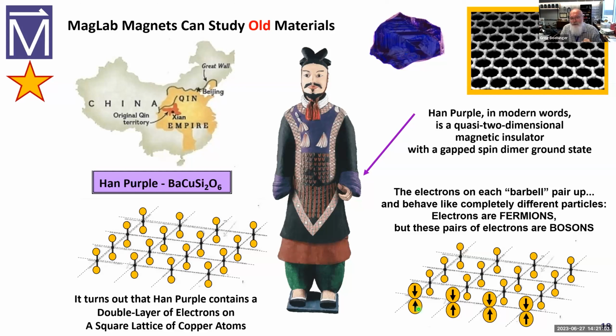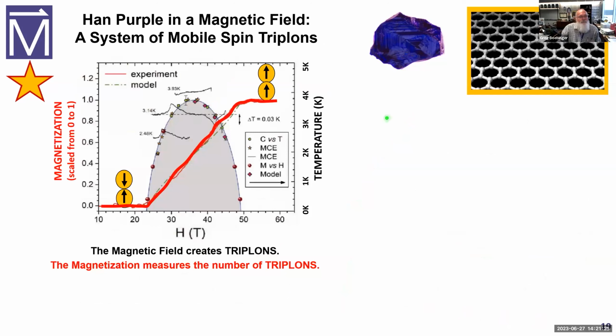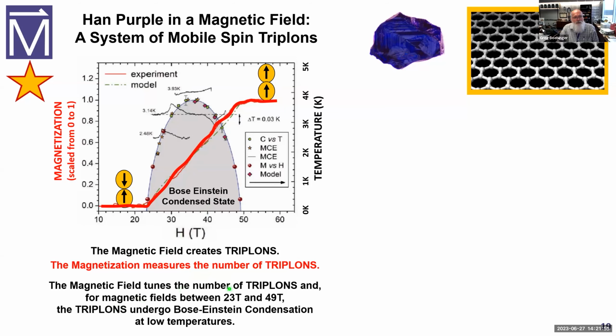And so now the total spin is 1 or 0. But in either case, particles with 0 and 1 spin are bosons, and whereas fermions try to stay away from each other because they have to be in different states, bosons like to be in the same state. And in fact, lasers are an example of this boson behavior where the photon particles like to all go into the same state. So in this material at 0 magnetic field or low magnetic fields, we have the original state where the pairs of electrons have their fields anti-aligned. But if you get to a high enough magnetic field, you start to align the spins until finally above 50 Tesla, all the spins are aligned. So these are called triplons for technical reasons I won't go into. And the magnetization goes up. It's measuring the number of triplons you have.